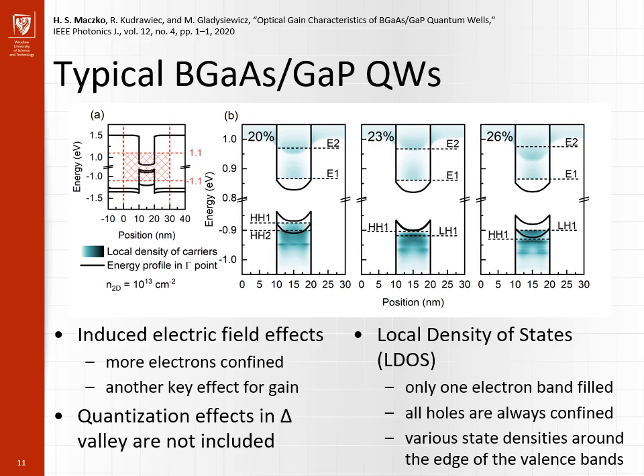entire structure. This is visible in figures B, where three quantum wells are presented: compressively strained with 20% of boron arsenide, matched to gallium phosphide with 23% of boron arsenide, and tensely strained with 26% of boron arsenide. Because of the delta valleys, noticeable electron current leakages in such structures should be expected, and some additional technological solution would be necessary to deal with them. However, arising from this, a positive charging effect allows more electrons to be located in the quantum well around the gamma point, and by this noticeably strengthens the gain.